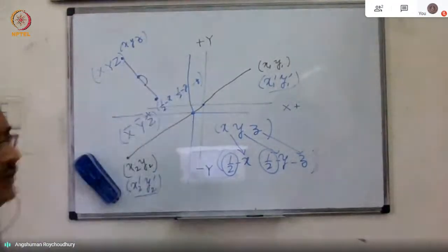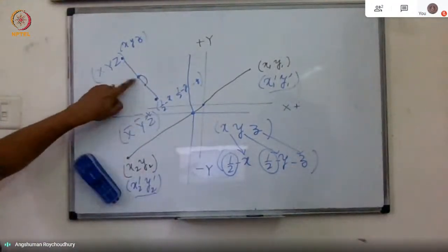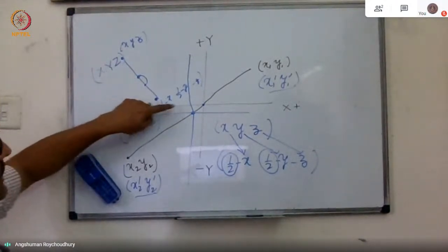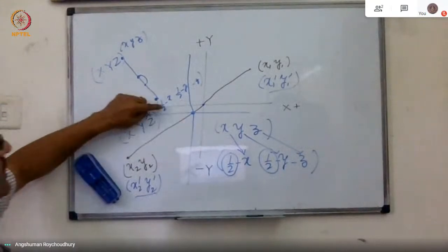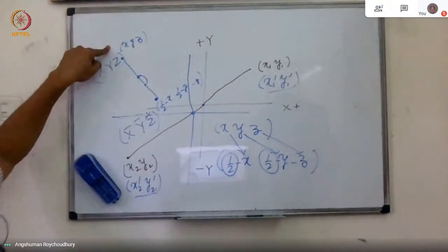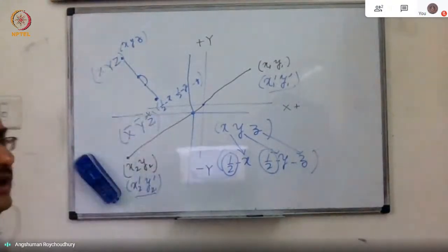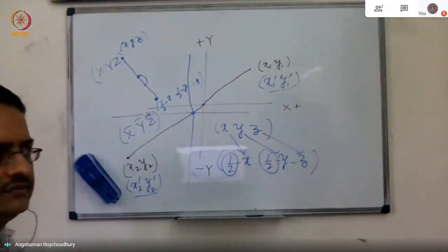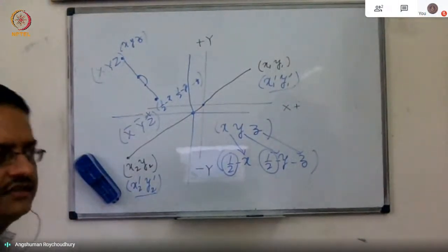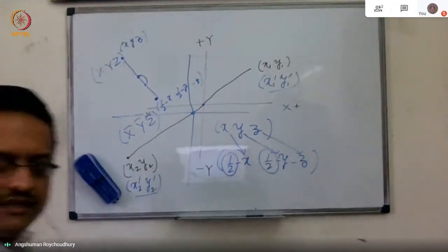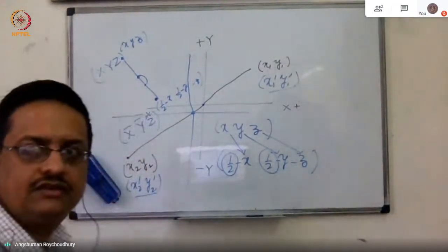So this new point should be shifted from here by what extent? By the extent of 1/4 along x and 1/4 along y. So that here we reduce 1/4, here we increase 1/4. So like that, the concept of 1/4 appears in case of origin shifting. So whenever you see the shifting of origin, you will see there is a translational component 1/4 either along x, y, or x and z, or only along z, depending on which system you are actually talking about.